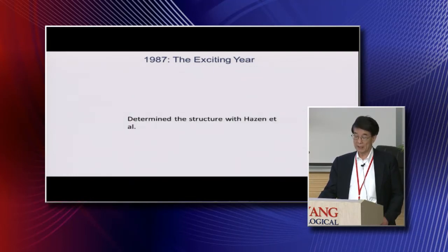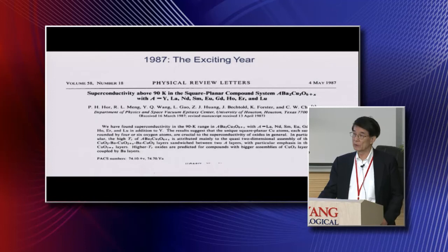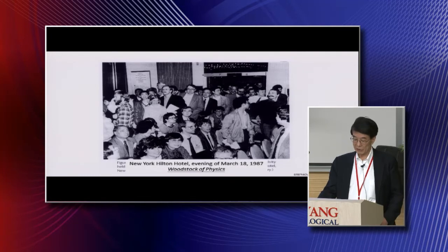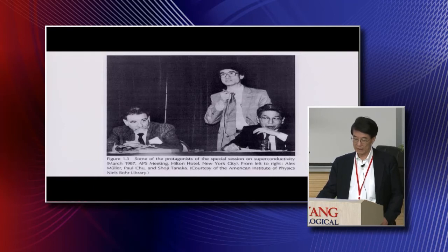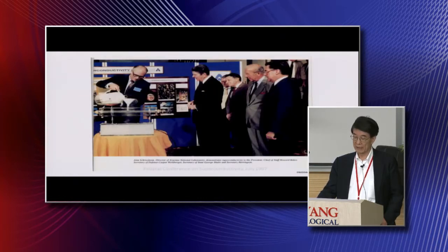So then came 1987, as I already mentioned earlier, and we, together with Bob Hazen at the Geophysical Lab, determined the structure, and then we did some testing. Immediately, we discovered a whole series of compounds very quickly, of the same structure. And that's the origin of the so-called Woodstock of physics on March the 18th in 1987, with thousands of people rushing in to listen to these results. And this is Alex Müller and Tanaka, Shoji Tanaka, there. And then even the great communicator, Reagan, with his cabinet members, tried to see magnetic levitation, as done by the then director of Argonne National Lab.